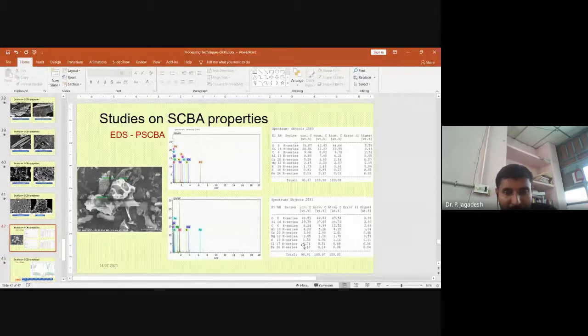With the help of EDS, here you can see the increasing proportion of calcium to silica ratio at different materials once it is processed. The proportion of calcium to silica ratio is increased, and even the proportion of calcium to aluminum is also increased.